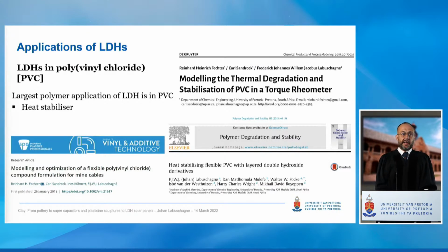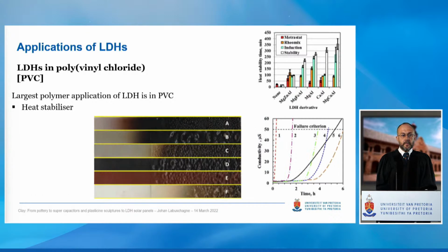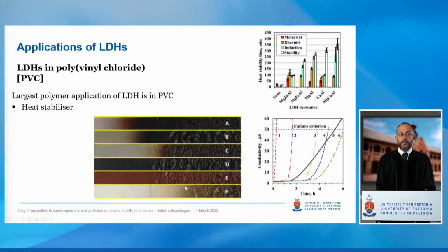One of the main applications for LDH since the beginning, specifically hydrotalcite, was in the PVC field. Hydrotalcite has been used since the late 1970s as a heat stabilizer in PVC. These three publications show our work in that field. Here I show a slide with the LDH as a PVC heat stabilizer. At the bottom and the middle, we have different samples, and what you need to look at is this blackening effect. Top is the PVC, which blackens round about there, and as we change the type of LDH at the same loading, that moves. So yet again, all LDHs are not the same.